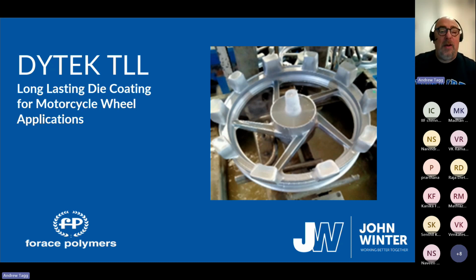So we had to develop a coating specifically for motorcycle wheels that gives the right high surface finish, but enabled the metal flow to fill these very thin web areas. These castings are quite prone to no-fill defects.